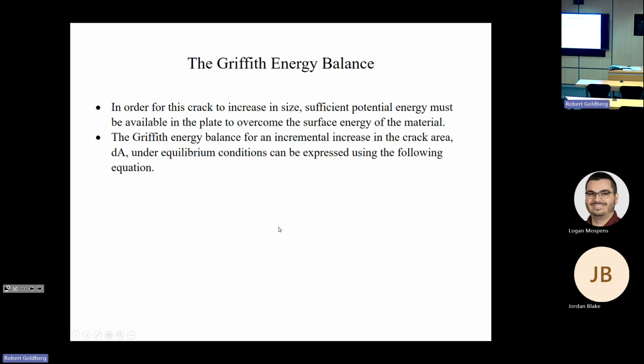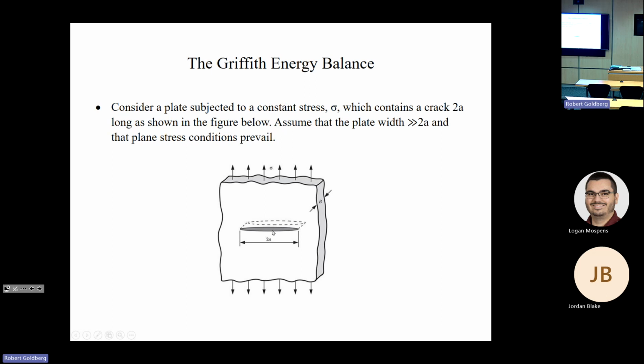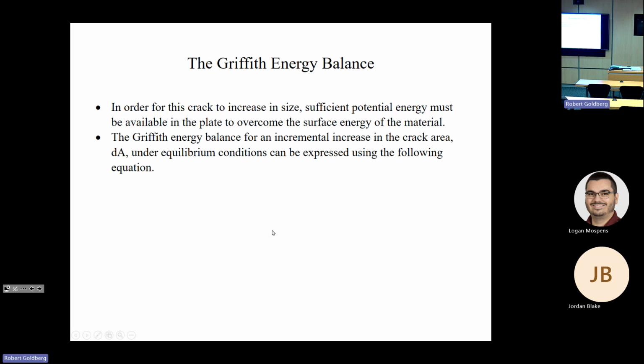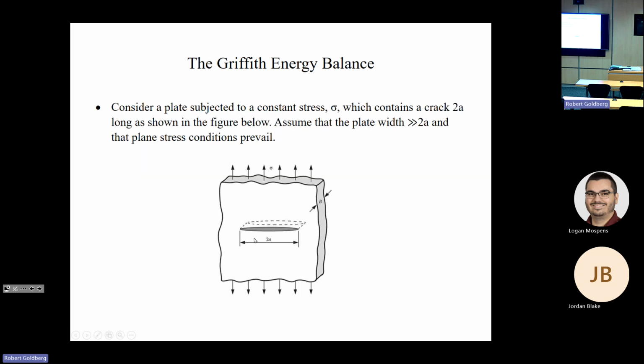So in order for this crack to increase in size, sufficient potential energy has to be available in the plate to overcome the surface energy of the material. So as we talked about two weeks ago in the last class, there's this inherent atomic bonding energy which holds a material together. So you need to apply enough energy to the plate to overcome these atomic bonds in order for a crack to grow. So Griffith defined an energy balance for an incremental increase in the crack area, dA, under equilibrium conditions. And when we talk about the increase in the crack area, we talk about this length 2a and the thickness B, because we were assuming in all this that the crack goes all the way through the thickness of the plate.